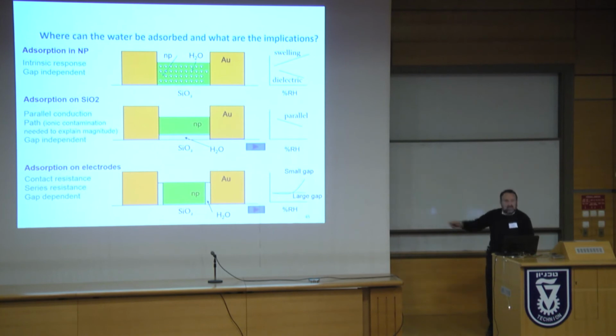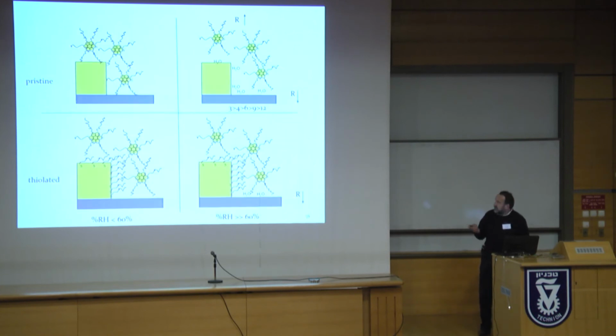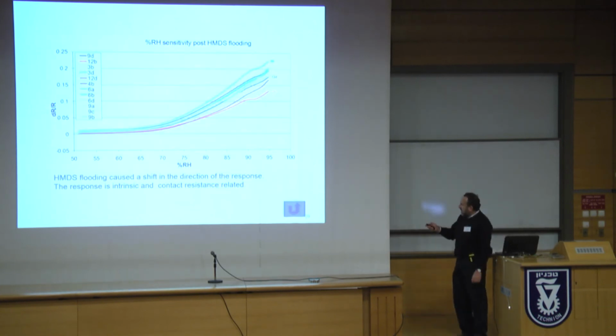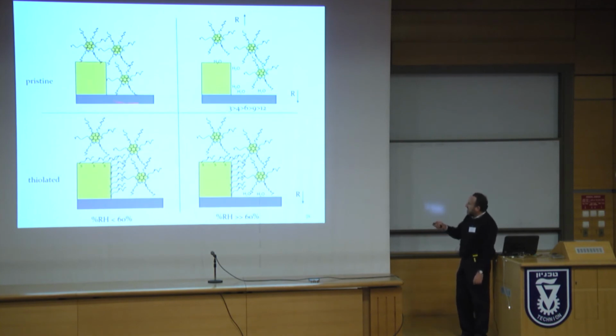Now, in this case, what we did is we covered the electrodes with octanethiol in order to make them hydrophobic, to repel water, and then to look what happens. So the idea was as follows. If this is the pristine situation when you have your nanoparticle and the gold, at high humidity, you can get water absorbed on the electrode or on the SiO2. When it's absorbed on the electrode, you get increase in resistance, and on the SiO2, you get decrease, and a strong gap effect in this case.